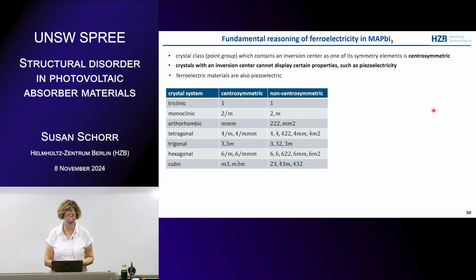Why is the space group so important? There were a lot of publications saying that MAPI is ferroelectric, and that the ferroelectricity in MAPI is also a reason for the high efficiency, because it accelerates the charge carriers when they go through the material. Now, from the crystallographic point of view, only a material which is non-centrosymmetric can show this property, because the centrosymmetric space groups have an inversion center. And materials with an inversion center cannot be piezoelectric and also not ferroelectric. This is just not possible.